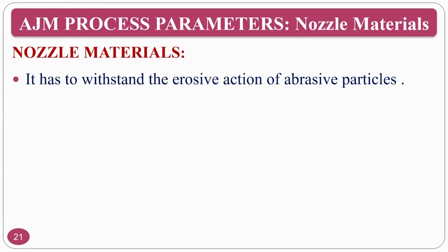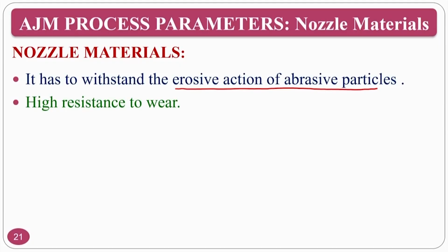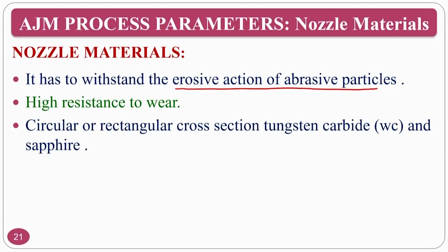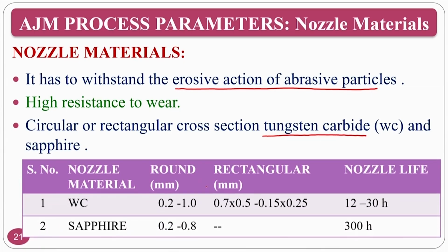It has to withstand the erosive action of abrasive particles that are passing through the nozzle, because the abrasive particles are mixed with the highly pressurized gas in the mixing chamber, and then it is pushed. That means that these abrasive particles also attack the inner walls of the nozzle. So the erosive wear of this particular nozzle should be less. High resistance to wear, that means that the nozzle should be fabricated from wear resistant material, with circular or rectangular cross section. Normally you can use tungsten carbide and sapphire. Sapphire is a commonly used material.